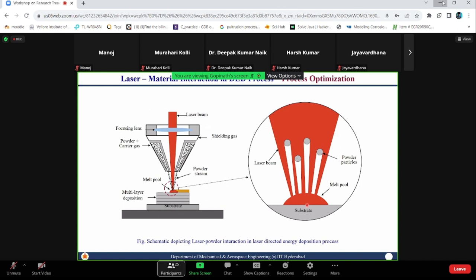And an oxidation process is always an exothermic reaction, so it will add some amount of heat. Because of such events, improper or inefficient shielding, or oxidation coming out of some particle, this kind of waviness will come in. Now the question is, how do I control this? Because this cannot be controlled by changing your velocity, because this is coming out of oxidation, or some random event or impurity, whatever you call it.